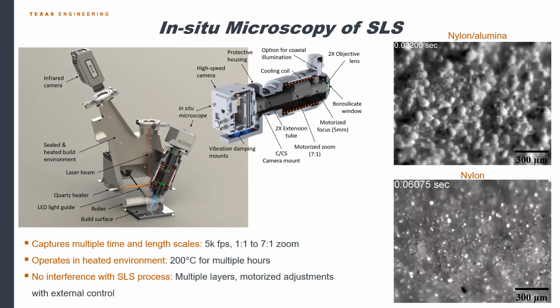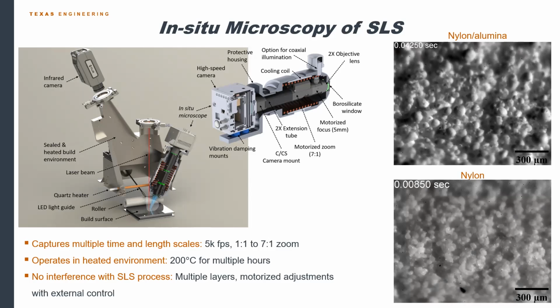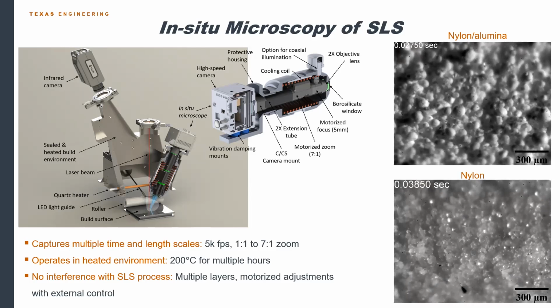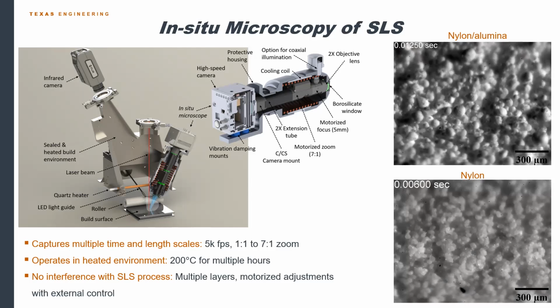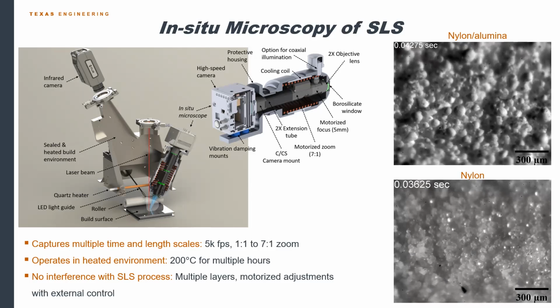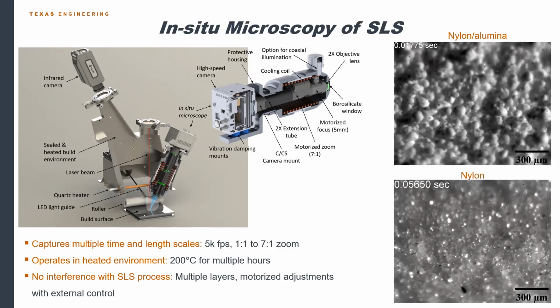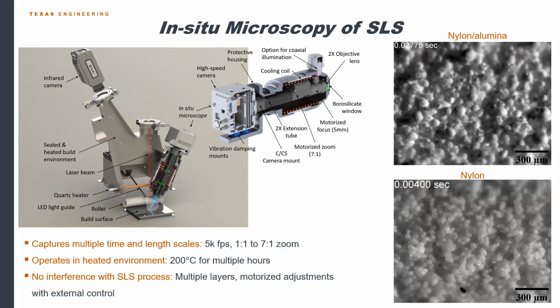The video on the top is scanning the mixed powder, nylon and alumina, at about 1,000 millimeters a second. And the white circle, which is kind of faint on the screen, represents where the laser is at all times. The bottom video is just plain nylon. So you can see in the top video, not much is actually happening. In the bottom video, after the laser passes, the particles become translucent, which is indicative of melting, and then they start to coalesce. So this led us to a new understanding that the powders behave differently during laser sintering. We actually developed a model to describe that.